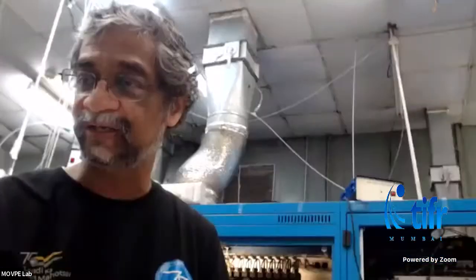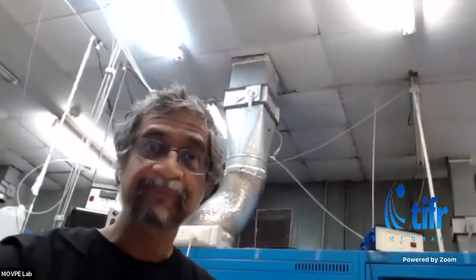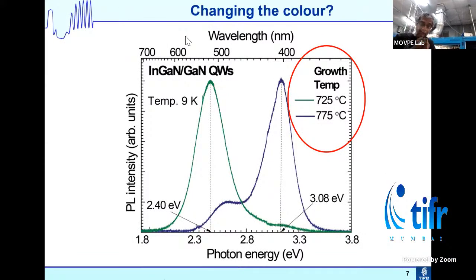Let me go to the next slide. I said you want to make LEDs of different colors, right? The simplest way to do it, remember, I have a reactor where it's very difficult to say, okay, put exactly 23% indium in. We can't control the indium concentration so much. The way we do it is by playing with things we can control. And this is again Preeti's work, where just by playing with the temperature, remember I said I can heat this up to 1200, that's the maximum. If I grow something at 725 or 775 degrees Celsius, it'll just depend. In one case you get blue, in the other case you get more indium, you get green. So that's what we do in our everyday research: we play with the parameters to change the kind of materials we grow.